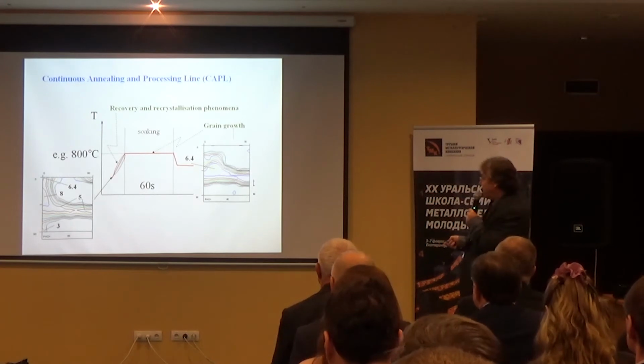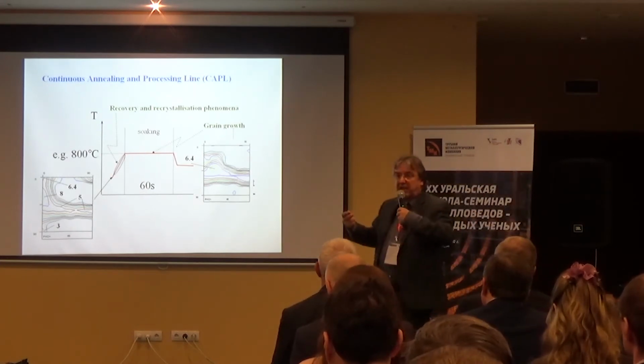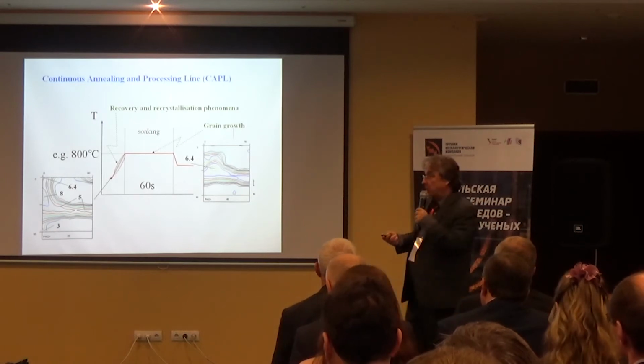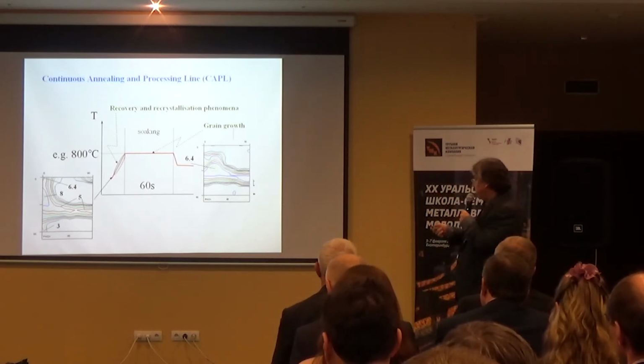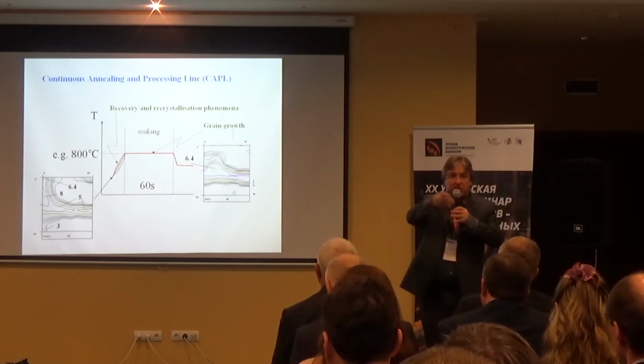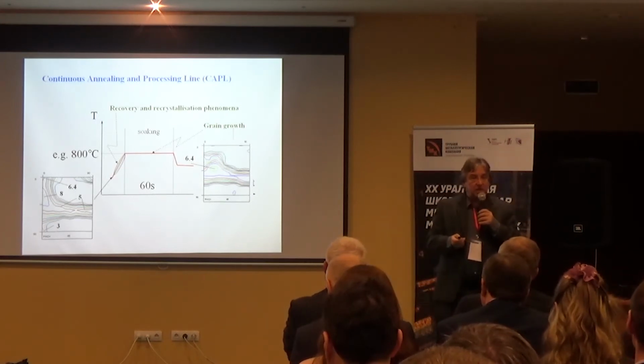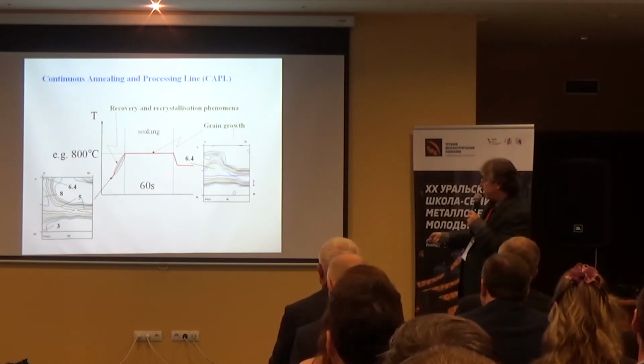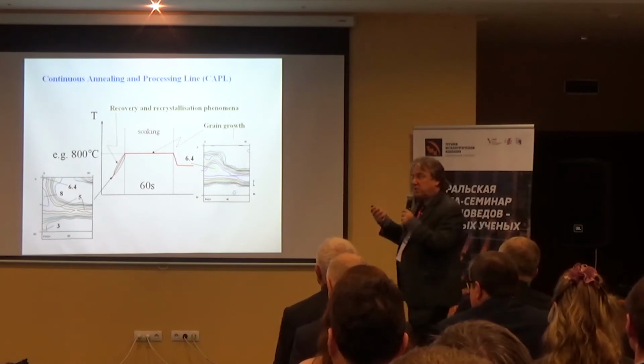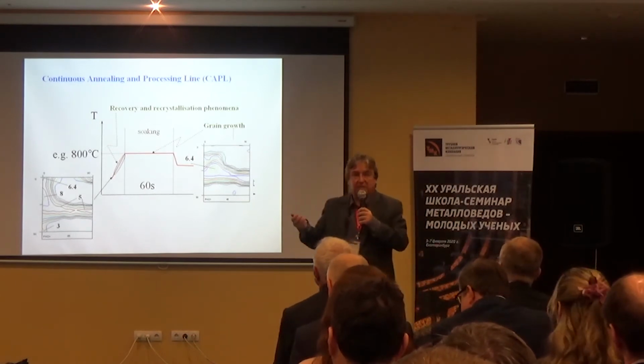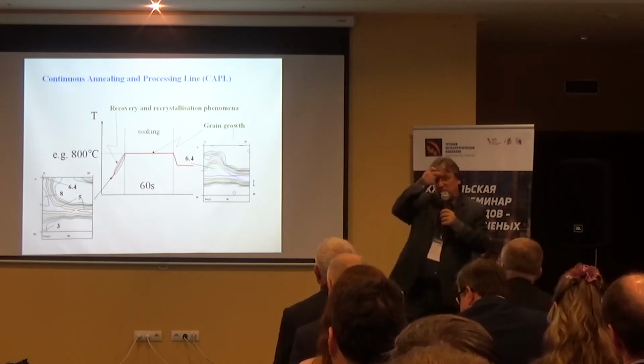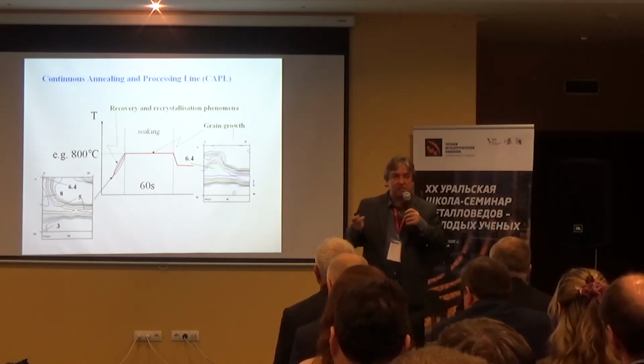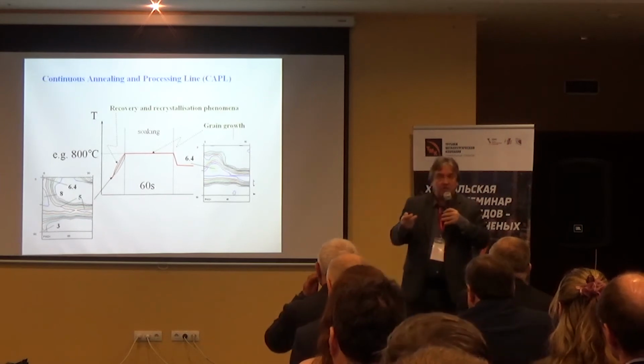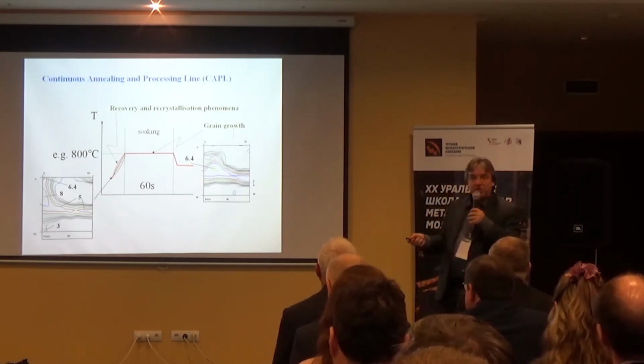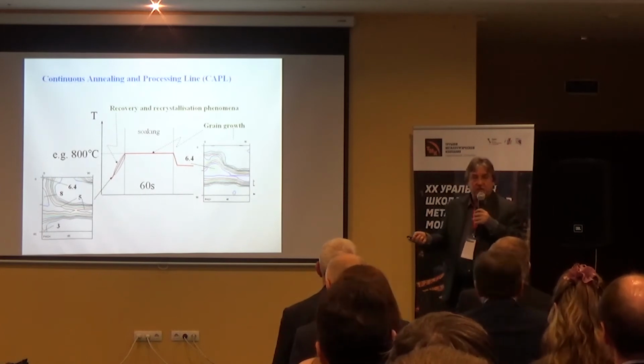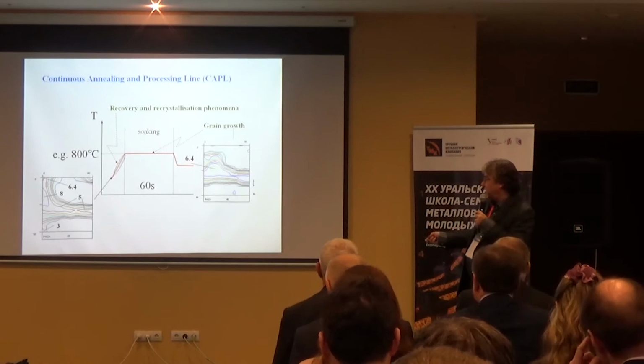These textures, they are very suitable. So this is the natural behavior of low carbon steel. So these textures are very suitable for deep drawing. If you see steel car bodies, it's very likely to have this type of texture. Actually, steel industry proclaims this as one of the big successes of texture control, but, well, let me tell you a secret. Steel industry was helped a lot by nature. The natural evolution of texture is to go to the BCC, to the gamma fiber texture.